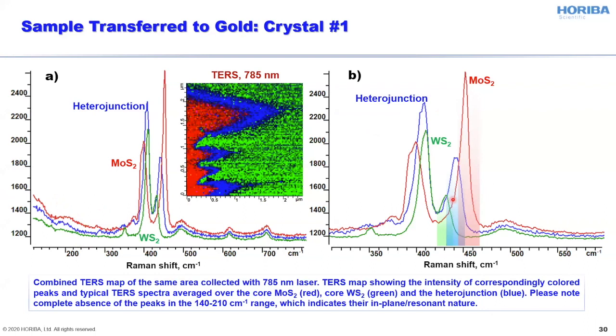Okay, so this discrepancy between the Raman spectra obtained with red and infrared laser actually can be quite important for interpretation of the nature of the peaks that we observe with resonant excitation.